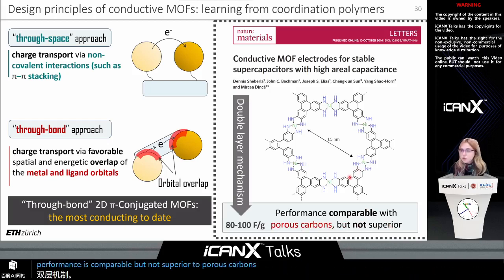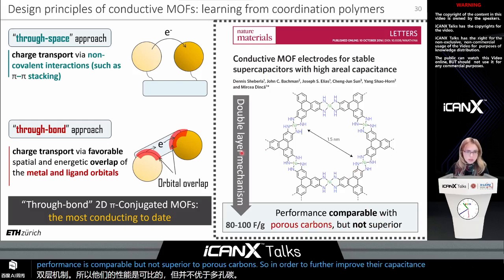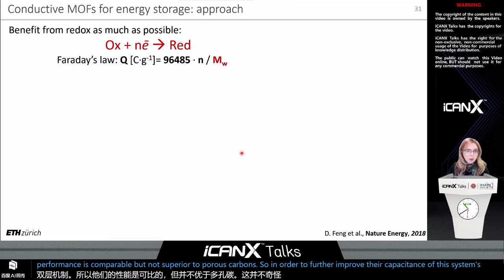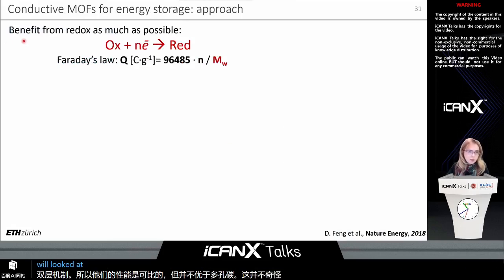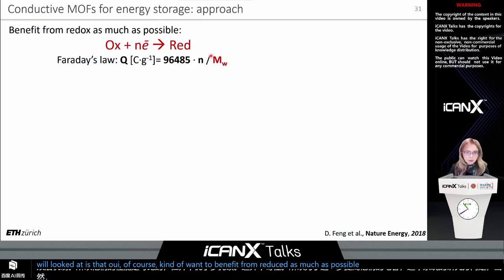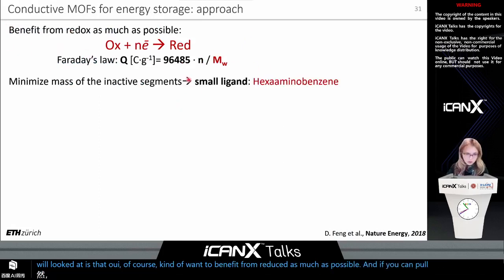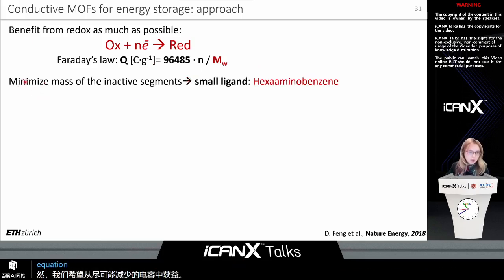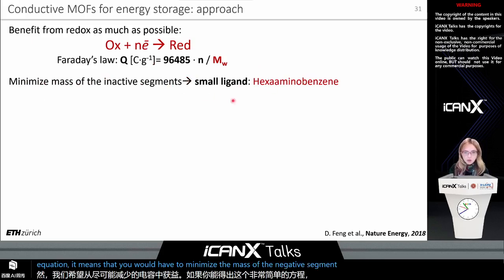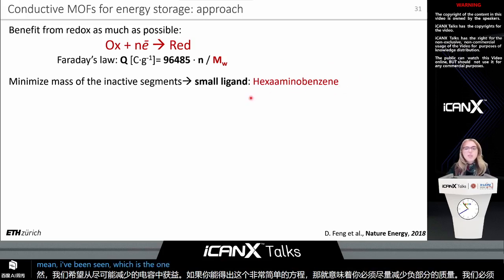So in order to further improve the capacitance of these systems, we of course want to benefit from redox as much as possible. And if you can follow this extremely simple equation, it means that we would have to minimize the mass of inactive segments, and we have to use a small ligand structure, hexaaminobenzene, which is the one that we used for this particular work.